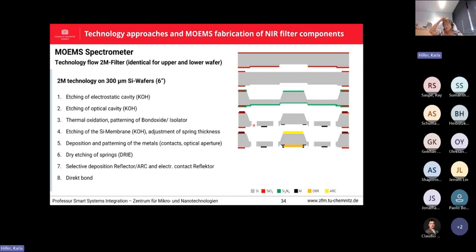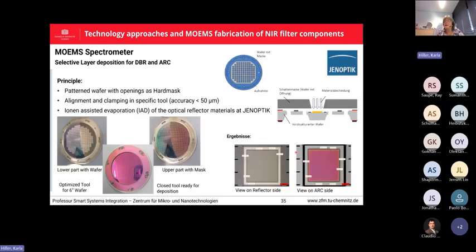And now this is the difference to the approaches before. The optical layers are deposited afterwards. So these yellow and orange layers will be deposited in a selective process, which I show in the next slides. And finally, the wafers are bonded together by silicon direct bonding. So how does the selective deposition work?